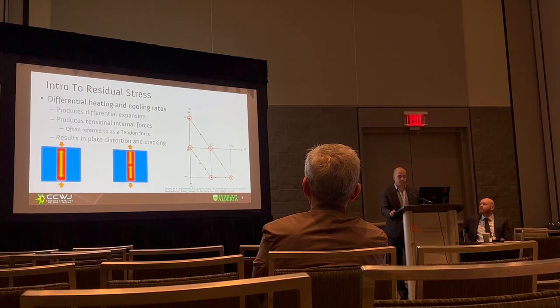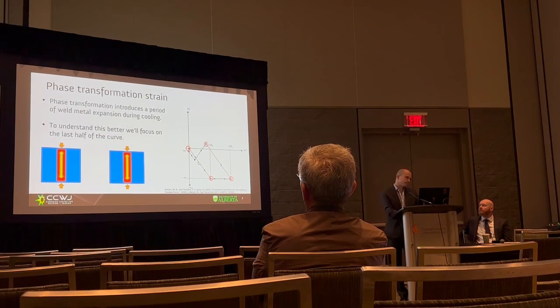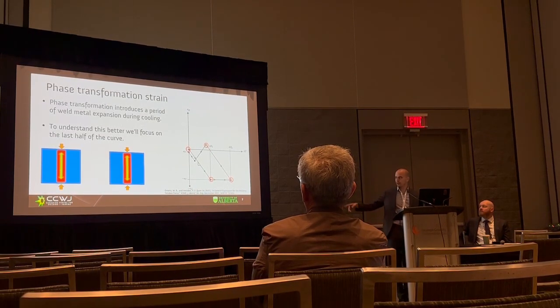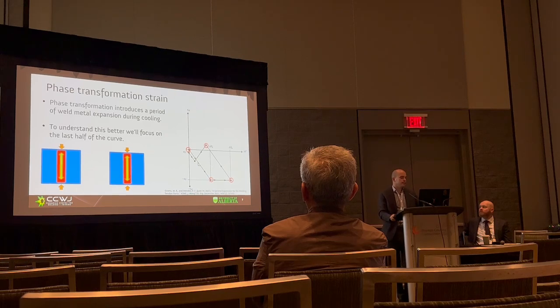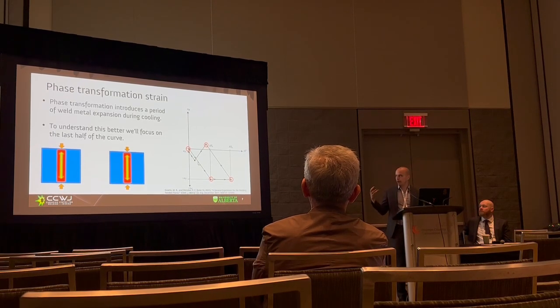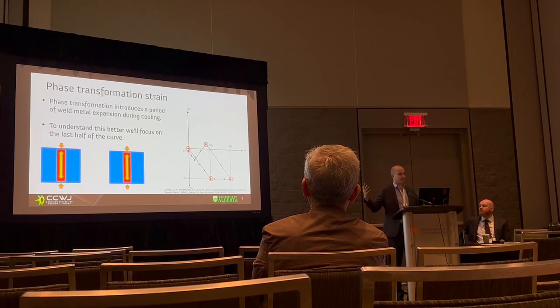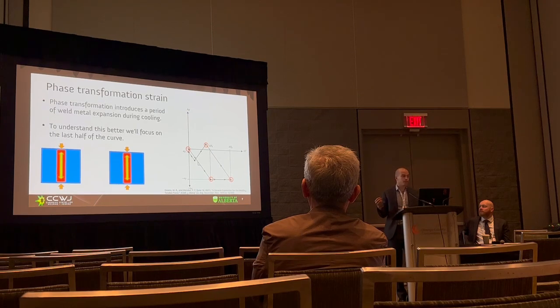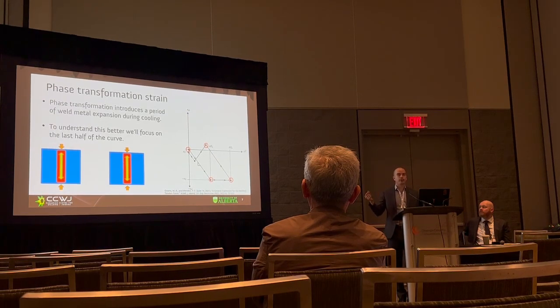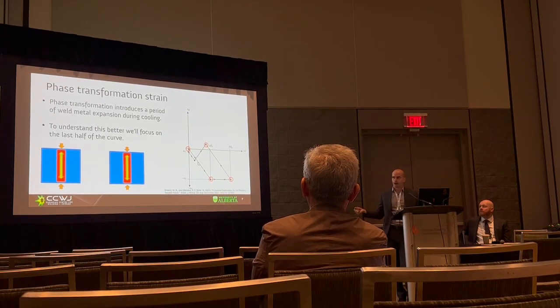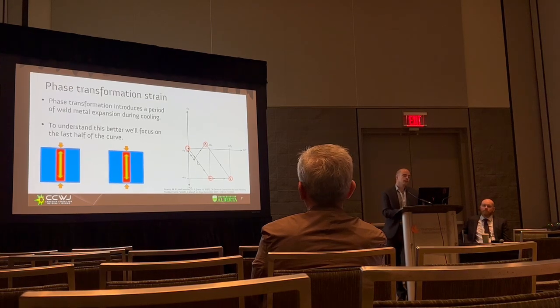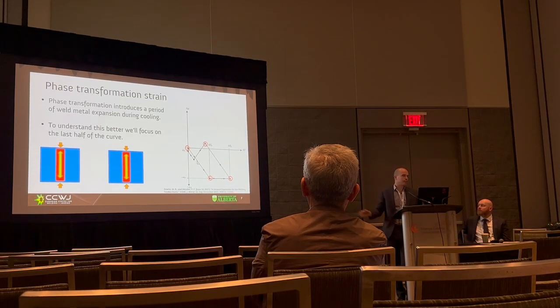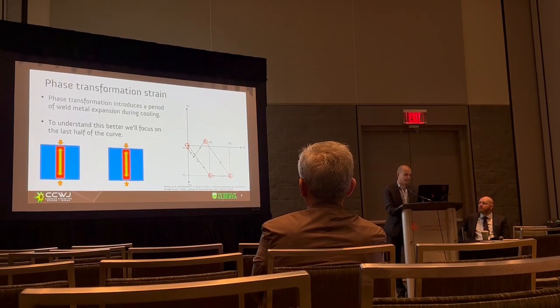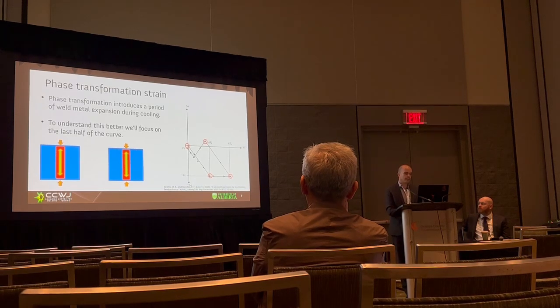So we know this is pretty standard, but that LTT alloy does something like this. So we can use that phase transformation strain. If you look at my second plate there, now it's that weld metal, when it went into the martensite phase transformation, it expanded, and now it's under compression because it's trying to be bigger than it was prior to welding, right? So you can see that it's dropped. Like I said though, it's nice to put it on a graph. How do we make any actual functional use of this? So from here, I'm just going to look at this plot.